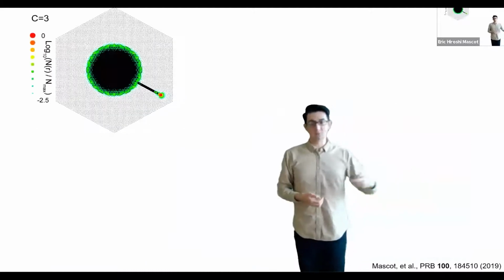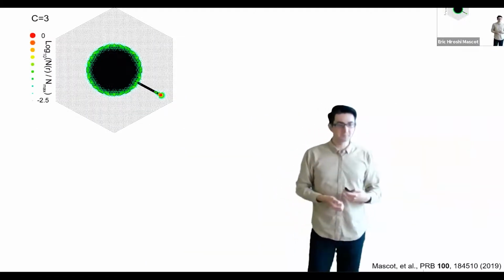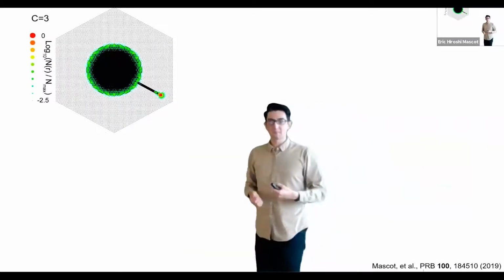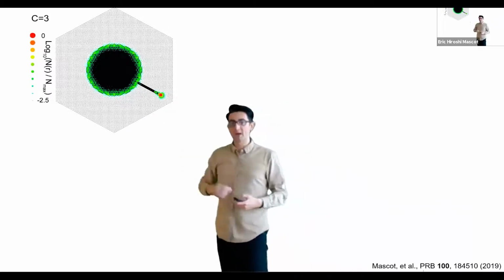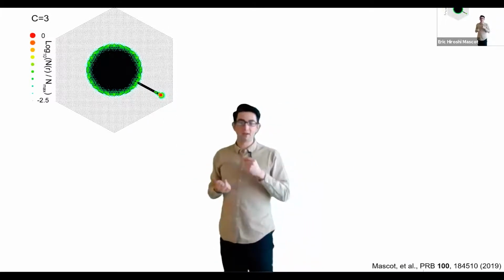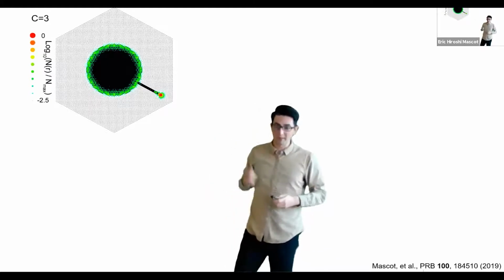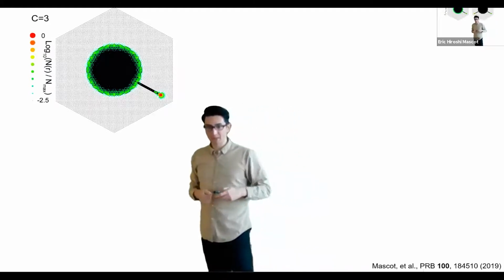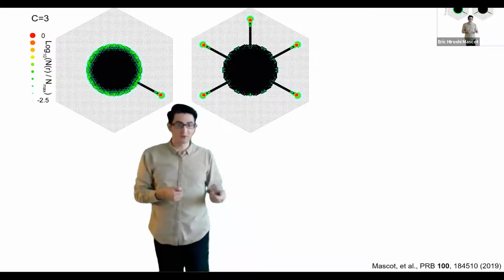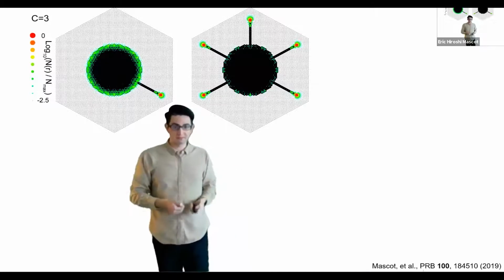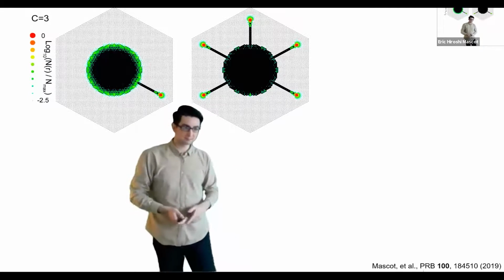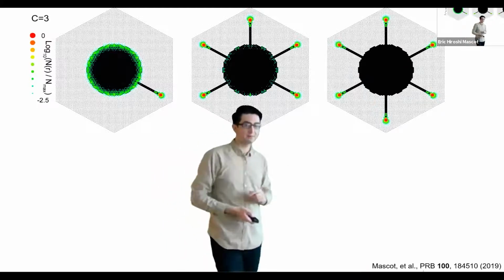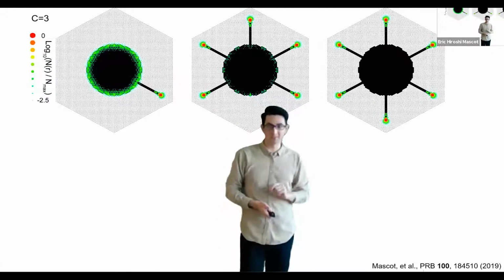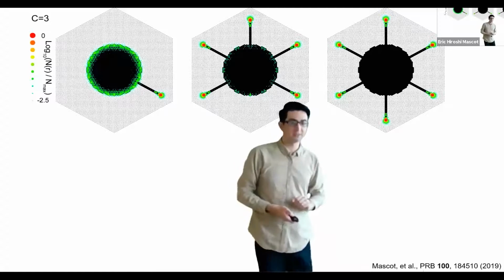This still works for C equals 3. And so here in C equals 3, we still have our edge state and a Majorana bound state at the end of a chain. And as we continue to add chains to our island, we start losing signature inside the island. But once we have 6 chains, which is 2 times the Chern number, we lose all signature inside of the island.